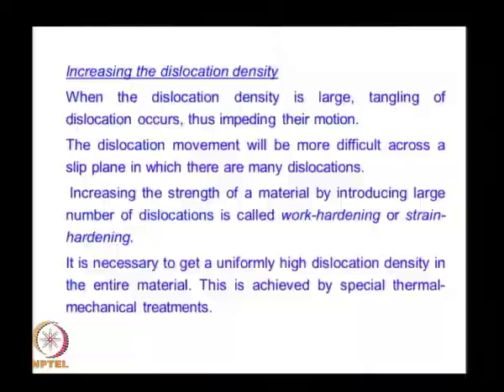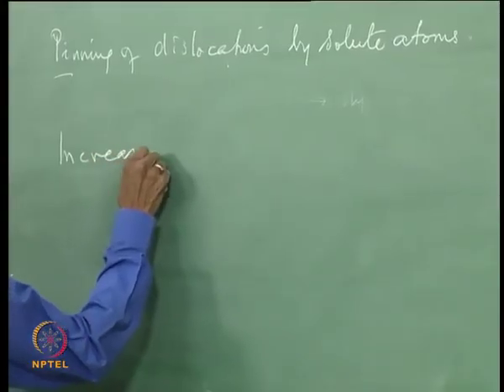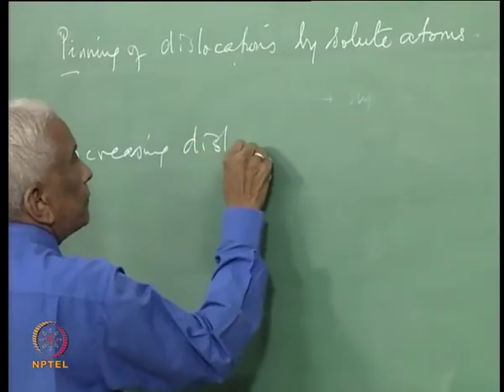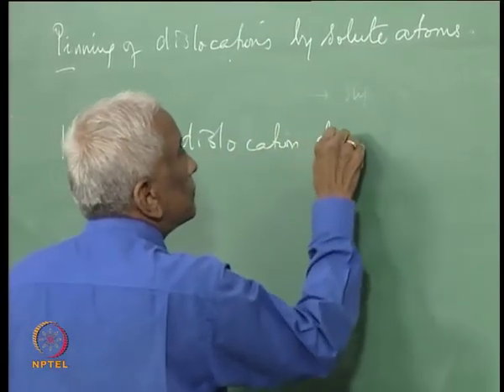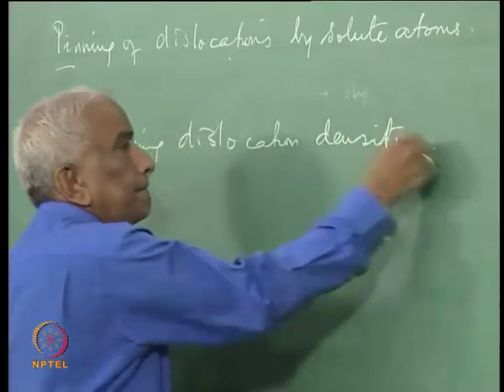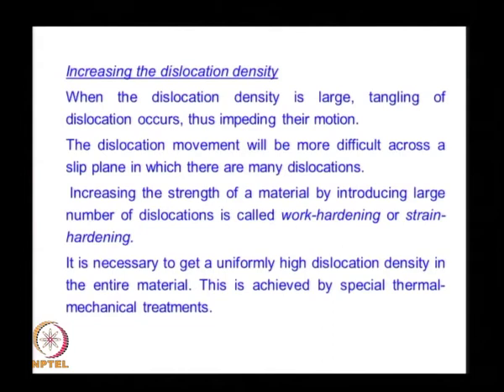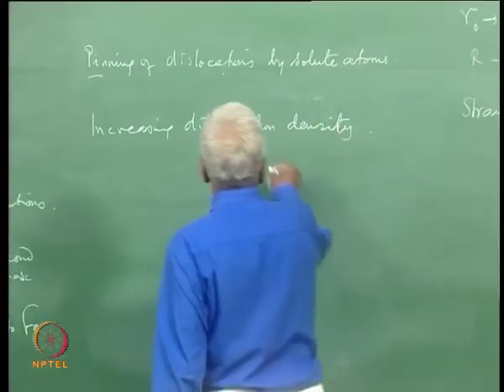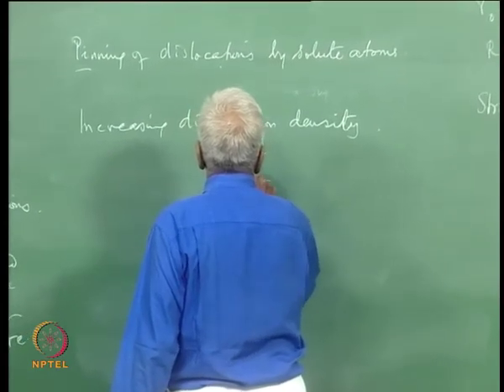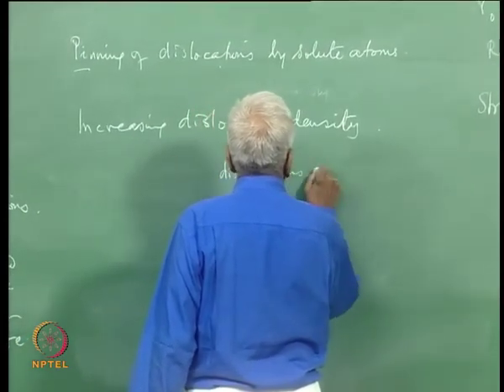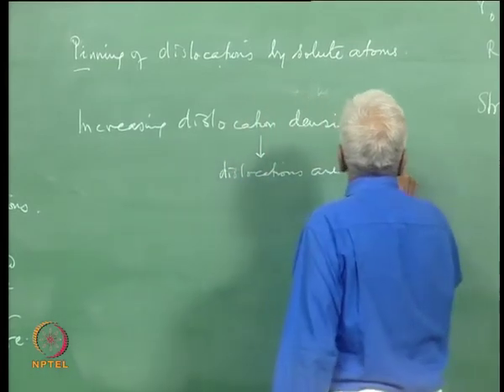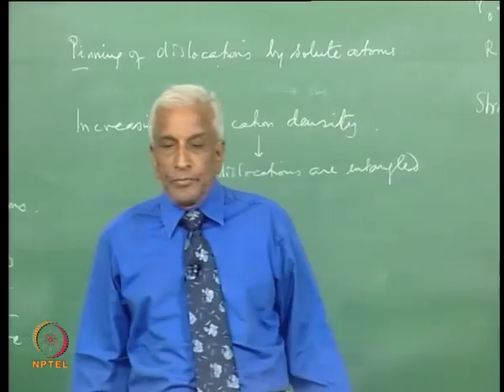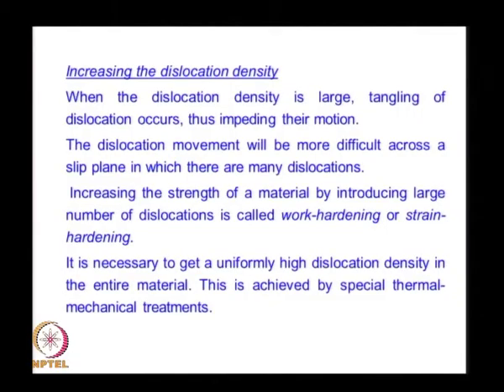Then you can also increase the dislocation density. You can introduce more dislocations. If the dislocation density is large, then the dislocations get entangled and thereby are prevented from moving. So, the dislocation movement will be more difficult across a slip plane when there are many dislocations. So, in order to do this, you do what is known as work hardening.